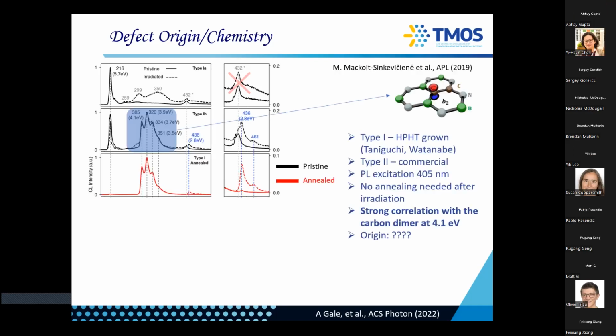Now, if you take the type 1B, you would see that it again has a very strong exciton line, so the quality of the hBN is good, but in addition it has these three typical peaks, called the 4.1 eV defect. It is related to a carbon dimer. It is one of the oldest defects that are studied or known in hBN.